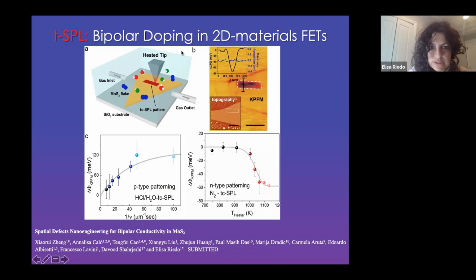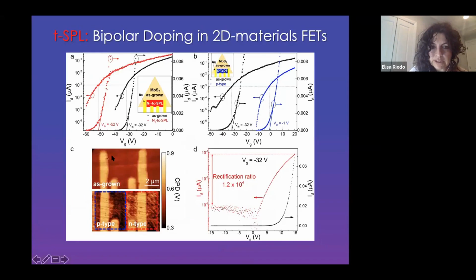As you can see here, there is a gas flow chamber where you can not only heat, but you can expose your surface to certain gases. So there is a chemical reaction between the heat and the gases present in the chamber. Depending on the gases that you choose, you can achieve either N-doping or P-doping. For P-doping, for example, you use a mixture of HCl and water, and for N-doping, you heat in nitrogen. So you can control N and P doping, so you can have a bipolar doping, and you can then fabricate a PN junction. This is what we have done.